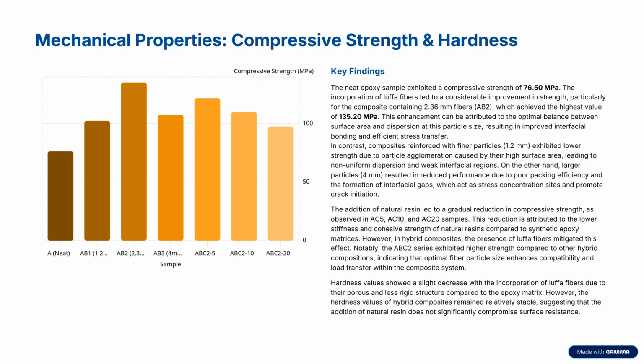However, the addition of natural resin led to a gradual reduction in compressive strength, as observed in the ABC2-5, ABC2-10, ABC2-20 samples. This reduction can be attributed to the lower stiffness and cohesive strength of natural resin compared to the synthetic epoxy matrix. However, in hybrid composites, the presence of Luffa fibers mitigates this effect. Notably, the ABC2 series exhibits higher strength compared to the other hybrid compositions, indicating that optimal fiber particle size enhances compatibility and load transfer within the composite systems. Hardness values show a slight decrease with the incorporation of Luffa fibers due to their porous and less rigid structure compared to the epoxy matrix.